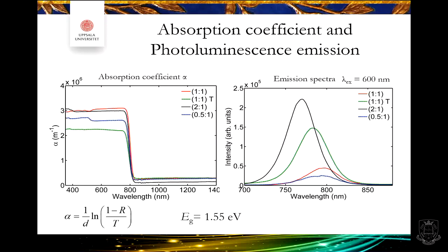Here we have photoluminescence emission. That is when you excite the electrons to the conduction band, and then you look at what kind of energy curve it looks like when they recombine. So the photoluminescence emission can be compared with the band gap and the position of the band gaps. And there you can also see if it is a little bit shifted, maybe you have excitons in your material and so on. But here you can also see the intensity of the different peaks vary a lot.